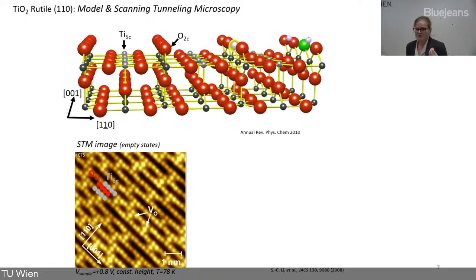Because we have this nice high atomic resolution, you can see vacancies—single oxygen vacancies—as bright spots in this image. Very often in metal oxides, it's not the perfect surface but these defects where the action happens. For example, when you have just a tiny little bit of water in your vacuum chamber, the water will come, dissociate, and put the proton to the next oxygen atom.